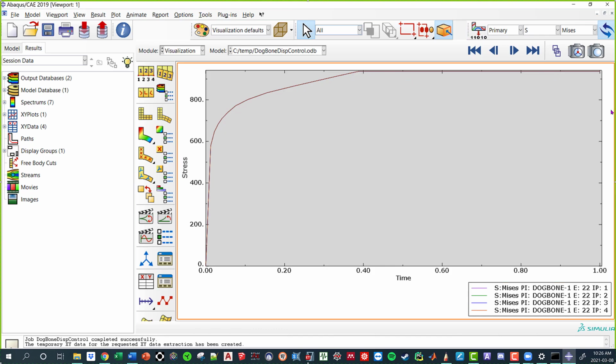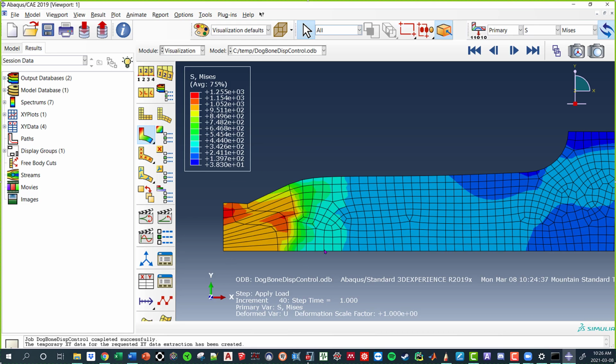went on forever. And that's the thing about displacement control. Remember when I said in ABAQUS, that last plasticity point that you guys input, ABAQUS just extends it out. And that's what we see here. It ran perfectly fine, and then it hit that point, and then it was like, see you later. I'm going on forever. So you guys can keep going on. Eventually, you guys will get an error saying that these elements are highly distorted. Be careful. So this is one of the things that we have to watch out for. Now, the last thing I want to kind of discuss here when it comes to this scenario.